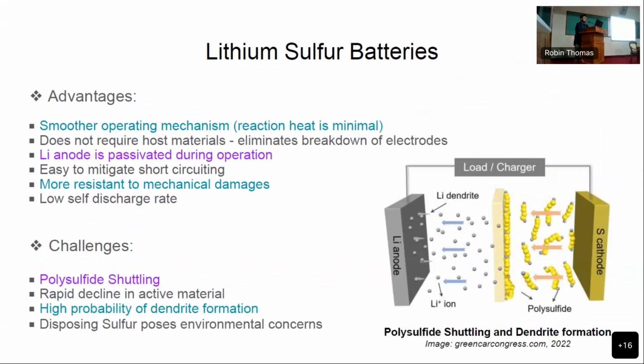I'll tell you why it's a disadvantage, because lithium is expected to form a complex of Li2S. That's all. But what happens is we have long chains of sulfurs which just get reacted with lithium, forming Li2S6 or Li2S8. So we can see that the efficiency of sulfur is sort of coming down when it comes to hosting lithium ions. It's quite an intricate concept, but you can understand that sulfur is not being efficiently used. So that's called polysulfide shuttling.